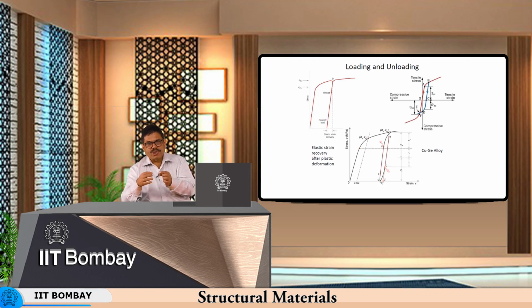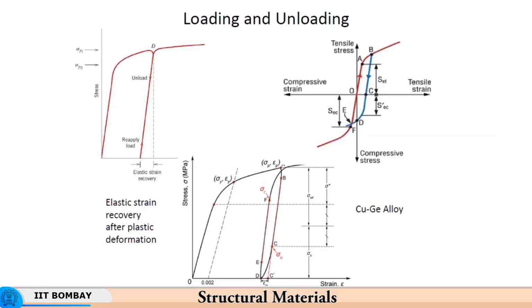Why? Because now the surface will get progressively softer and softer, because the direction of stress is changing and the yield point has been exceeded. Initially the yield point was exceeded in tension. So, in compression it yielded at a much lower yield point. Again, when it was subjected to tension, the yield point was further below.